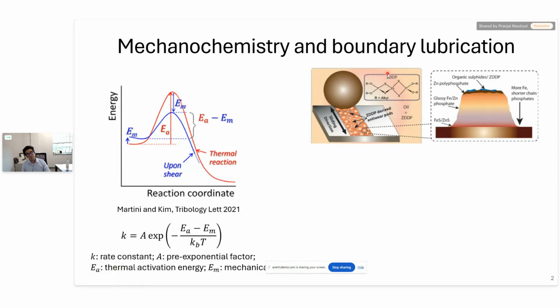This additive reacts at sliding interfaces because of mechanical stresses and heat to generate tribofilms, right? These are surface-bound films which consist of phosphorus, sulfur, zinc, iron. So essentially glassy phosphate films. And once these films form on the surfaces, they protect the underlying metal from wear because of elevated contact stresses.